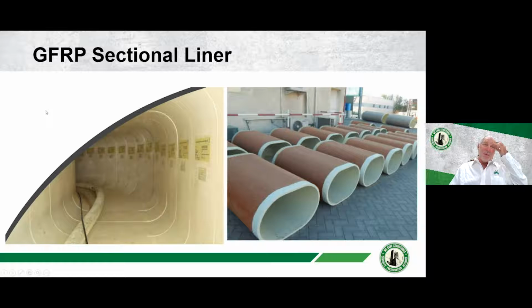Another one that's similar to that, but a little more fancy, is a fiberglass sectional liner. These are sections of fiberglass that are specifically designed in the shop based on very, very tight measurements that you take in the field. So you actually have to go out into the field, make measurements all along the pipe, create the fiberglass liners, and then take them, install them in place, seal the joints, and then grout around the outside. Fairly labor intensive, but it is a very, very effective system, again, where you've got high chemicals because of the chemical resistance of the fiberglass.